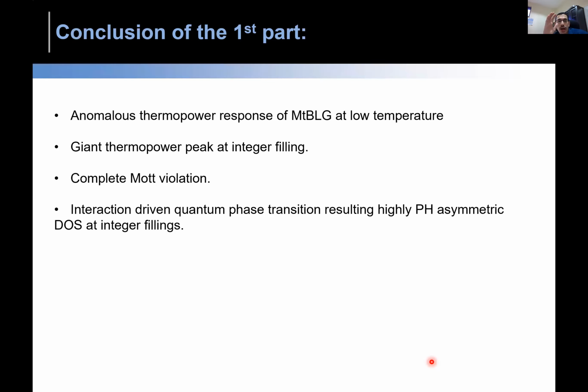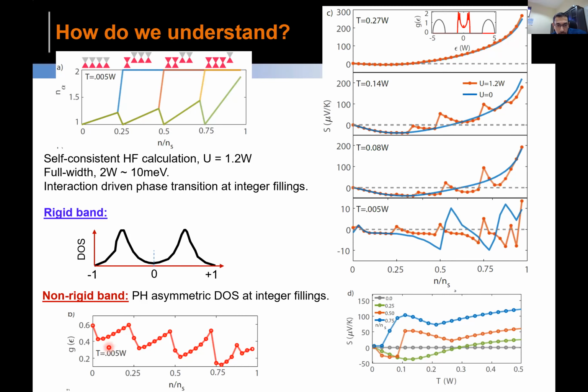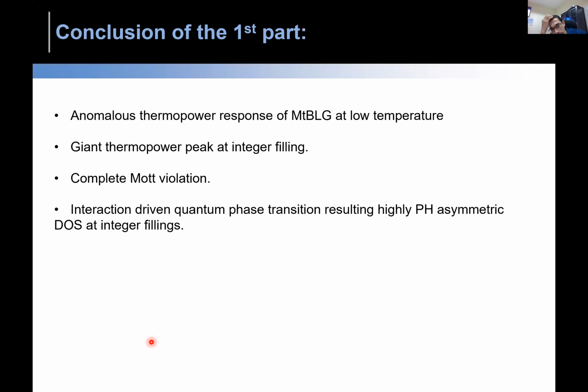Let me end this talk by saying what I tried to give you: how magic angle twisted bilayer graphene has importance, and how our thermopower could recognize this anomalous thermopower response, which is important to show the Stoner-like transition at integer filling. And because of this particle-hole asymmetry, you see these slopes are different. This side falls quite rapidly, while on this side it does not, so there is a particle-hole asymmetry. Because of that, the thermopower peak was appearing. And of course, it shows a very nice example of the Mott violation and so on. I think I'll stop here.